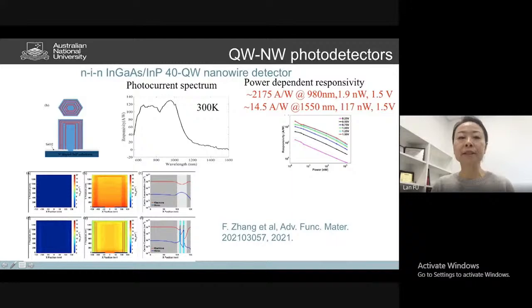In this way, we achieve these very important detection wavelengths for photodetectors. And because of this unique radial transport, remember our quantum wells are radial, dominated by the radial component, if you apply bias to collect your photo-generated carriers, because of the radial morphology and carrier path, we can achieve very fast, efficient collection. You might also achieve some optical gain inside this transition process. Thereby, we can achieve high responsivity of the detector at both 980 nanometer as well as 1550 nanometer wavelengths, which is very useful for a lot of applications.